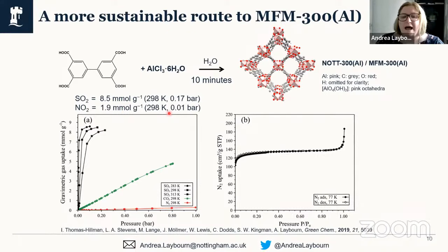To add to our interest as well, the conventionally prepared material is not porous to nitrogen. However, we had a look at the nitrogen uptake to see if we saw any differences, and we did find that we got some nitrogen uptake for this material. Now, in order to rationalize this uptake with the dioxides, we know from studies done in the Schroeder and Yang groups in Manchester and in Illich Ibarra's team based over in Mexico, that the interaction between the MOF and the dioxide pollutants is typically across this secondary building unit backbone via an aluminium hydroxyl interaction.